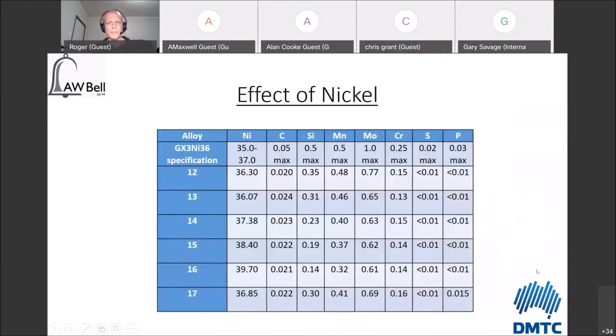The effect of nickel was looked at next, and we were looking at a number of different alloys here. 6 different materials were looked at, with nickel contents up to around 40%, keeping everything else pretty constant. Again, this is still air melting, nothing done in a vacuum or anything like that, using an argon purge through melting.